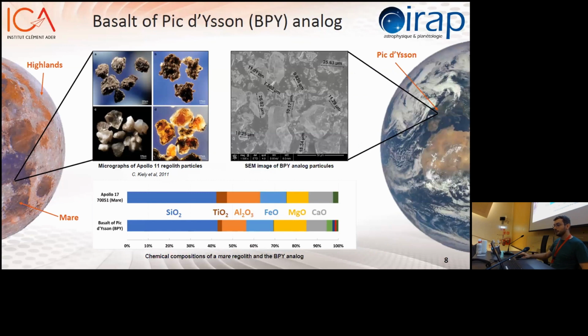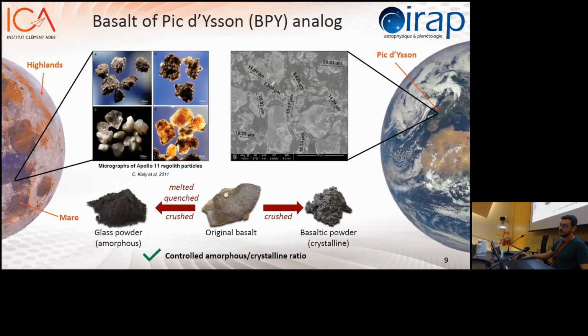And so a few decades ago, my PhD supervisors found a place in France, which is called the Pic d'Ysson, which provides us a basaltic material that is quite close to what we could find on the Mare regions, with a quite low content of titanium, as you can see in the chemical composition at the bottom of the slide. And a huge aspect of this analog is the fact that the original basalt in itself is 100% crystalline. So what we can do is melt it, quench it, and crush it to have this glass powder. And so just by mixing the original basaltic powder with glass powder, we can really control precisely the amount of glass material we have in the analog.